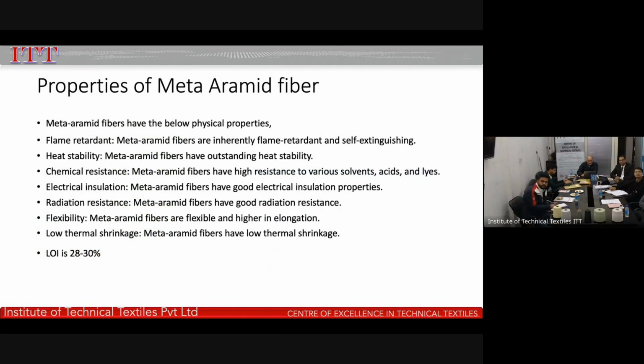Meta-aramids are inherently flame retardant. They have good heat stability. Chemical resistance is good. Electrical insulation is also good. Radiation resistance is good. They have flexibility and higher elongation. Meta-aramids have low thermal shrinkage, and the LOI is 28 to 30%.